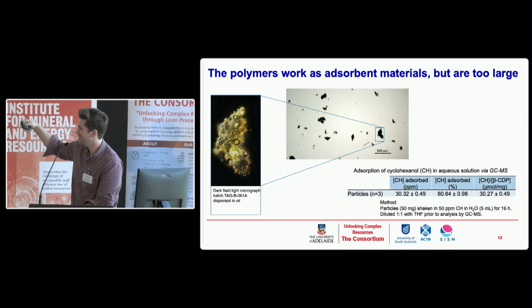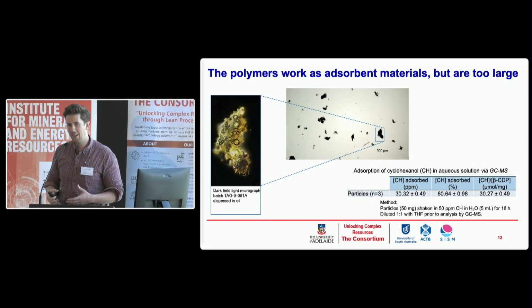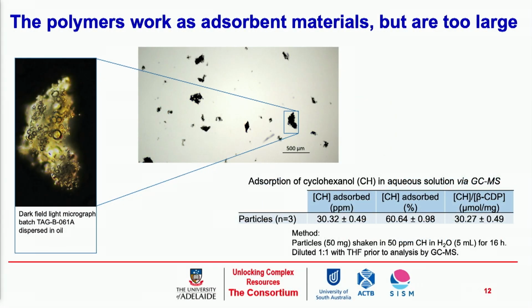Basically, when we first made these, it was produced as a large sort of monolithic structure, which required a lot of grinding. It was kind of hard to work with. These were quite large, which was ultimately not suitable for further adaptation down to the Quartz Crystal Microbalance system. But we started to evaluate their adsorption properties, and we can see that they're interacting with the components that we want in a sort of scale that would be useful.